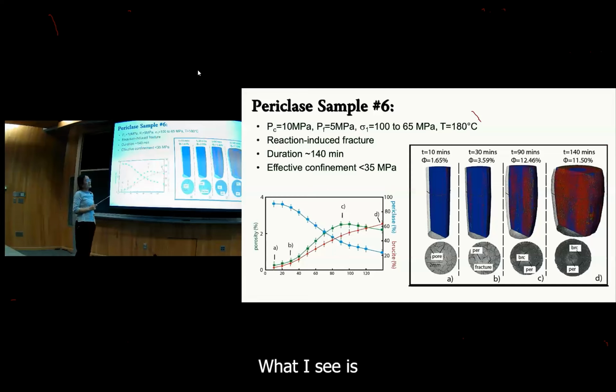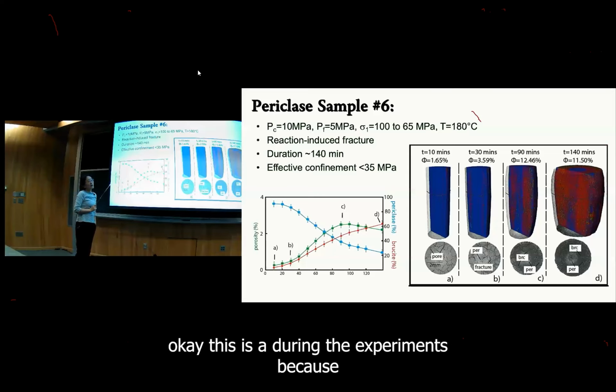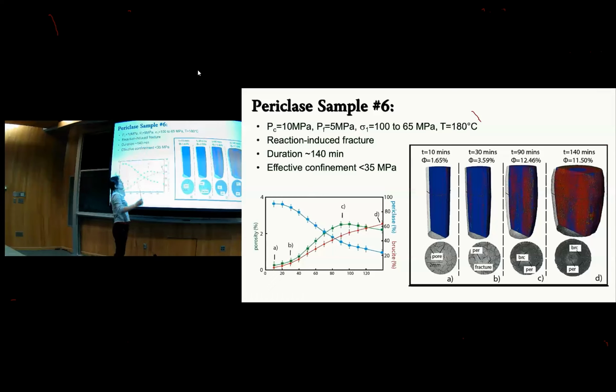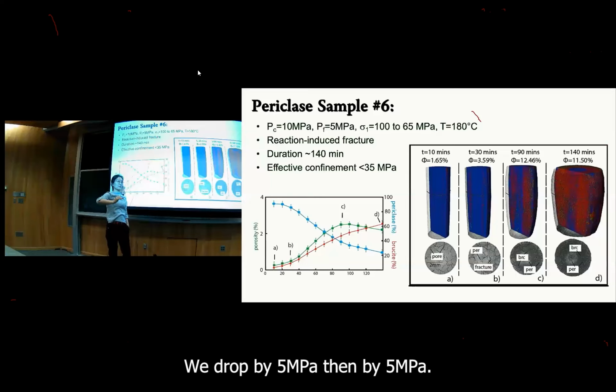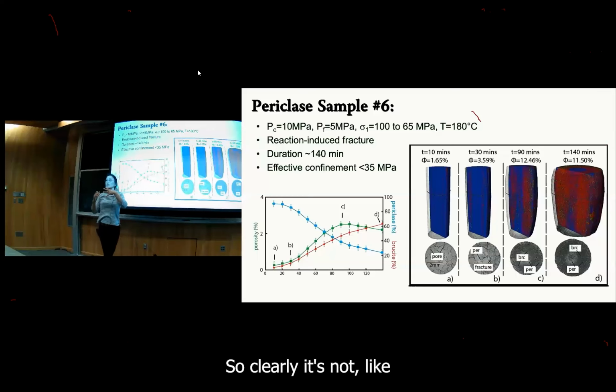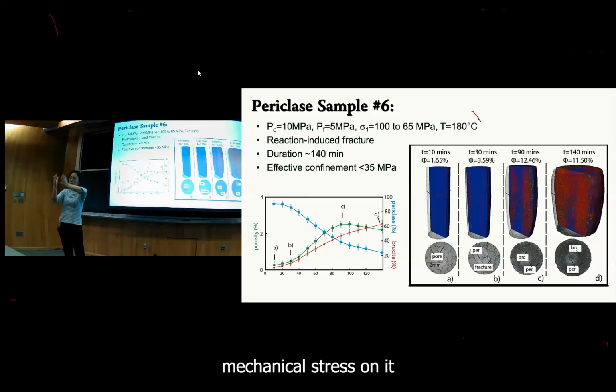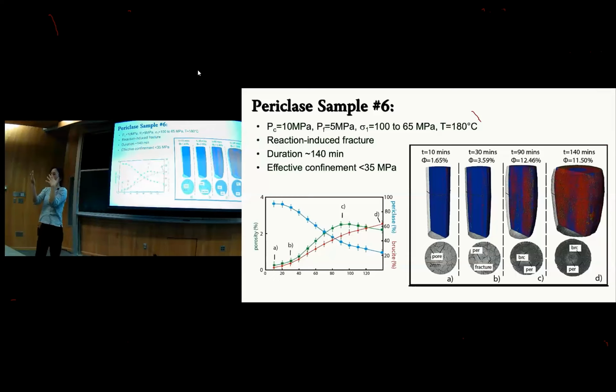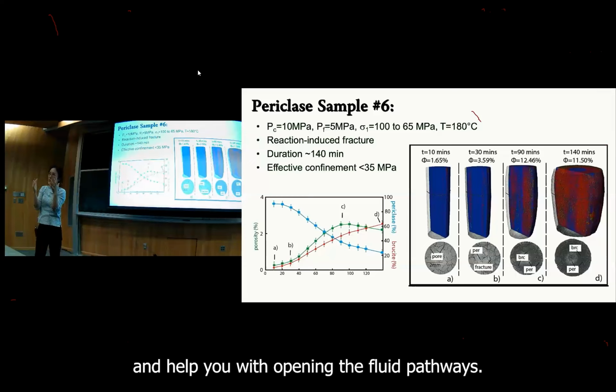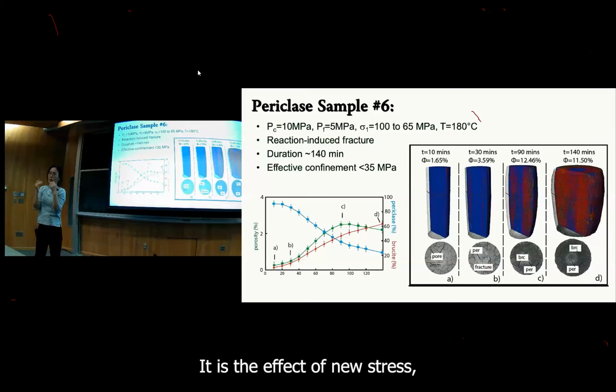What I see is, as soon as I increase that, the reaction starts to slow down and then stops. I was puzzled, but then I said, okay, this is during the experiment. Because the thing started to stop, I said, let's drop this. We dropped it 5 MPa by 5 MPa. When we dropped to 65 MPa, the reaction restarted. So clearly it's not that you put some mechanical stress on it so the fracture can slide and helps you open the fluid pathways. It is the effective mean stress.